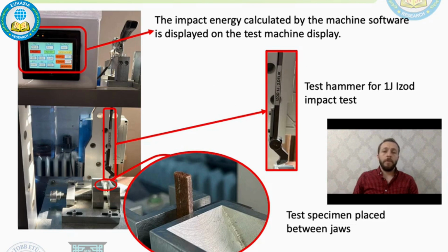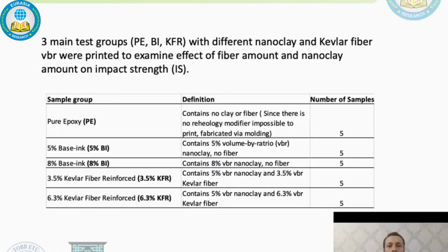Tests were carried out with a 1 joule Izod impact test hammer, and the impact energy calculated by the machine software was seen and recorded on the test machine display in the left corner. Test samples. To examine the effect of fiber amount and nanoclay amount on impact performance of 3D printed composites,